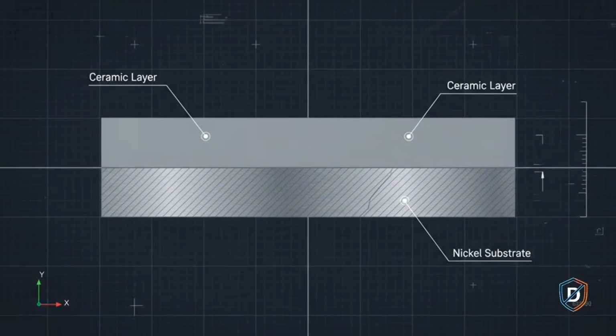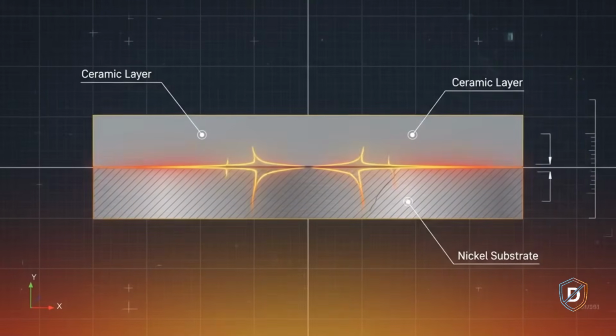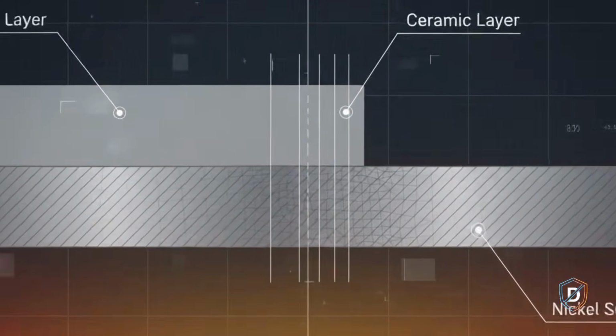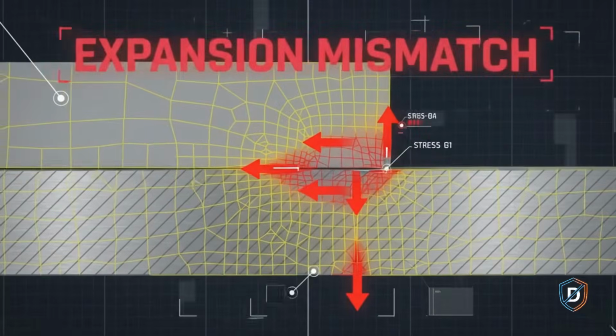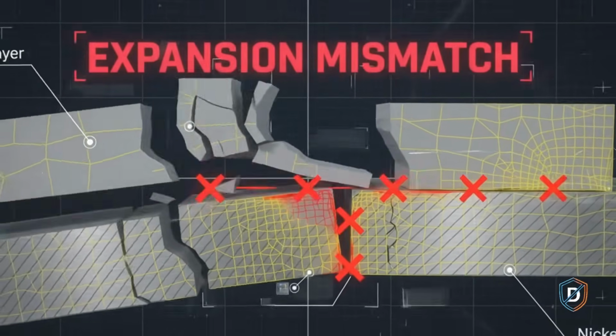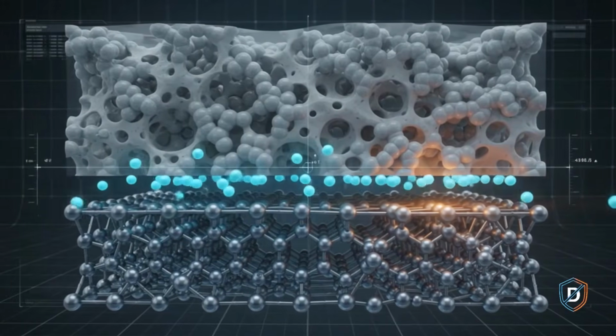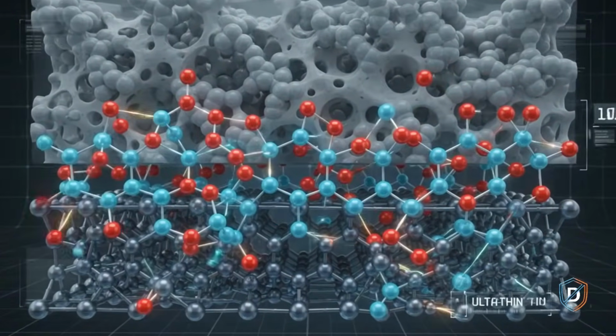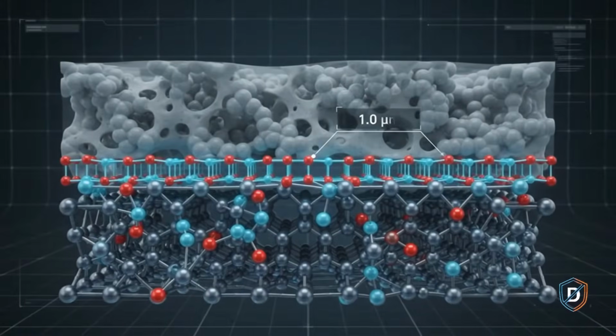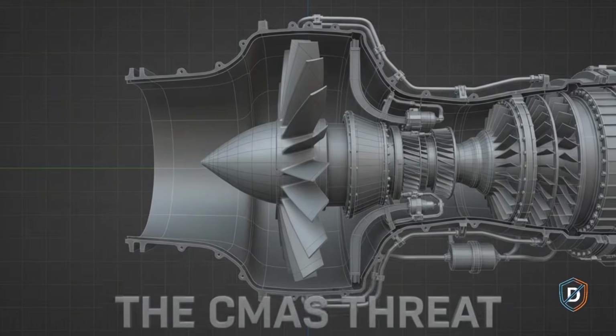The real nightmare is thermal expansion. Nickel expands twice as fast as ceramic. If locked together directly, the ceramic coat would peel off like old paint. The engine fixes this by growing its own glue. At high heat, aluminum inside the blade bleeds to the surface. This forms a self-healing layer just 1 micron thick.